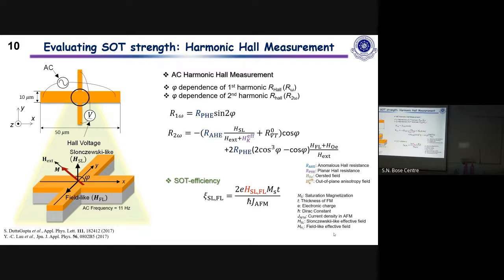And what we measure is this transverse voltage, but we measure the first and second harmonic voltage. The first harmonic resistance, if you work out this equation, corresponds to the planar Hall signal coming from the magnetization. And the second harmonic resistance contains information from these current-induced torques, as you can see in this coefficient and also in this coefficient.